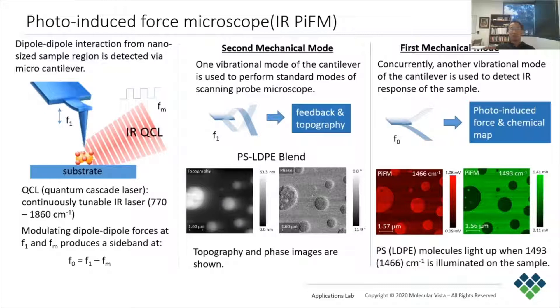This sideband detection measures the gradient of the photo-induced force and is characterized by sub-10 nm spatial resolution and excellent surface sensitivity. By using two lock-in amplifiers, both the standard AFM and the photo-induced force data can be acquired concurrently.